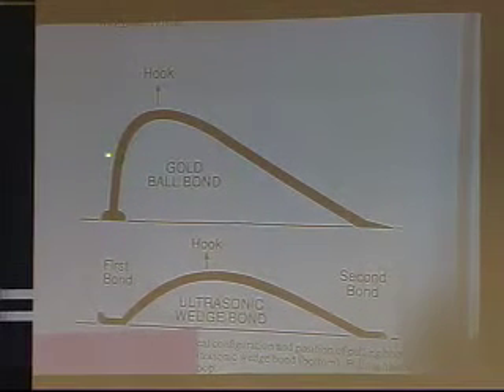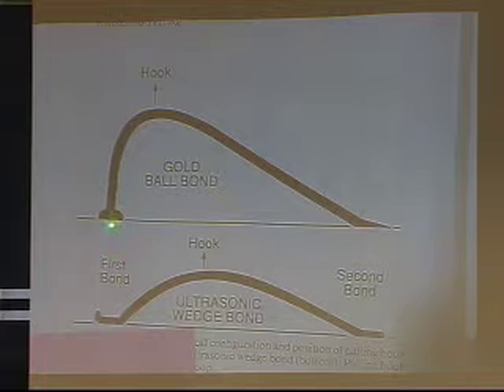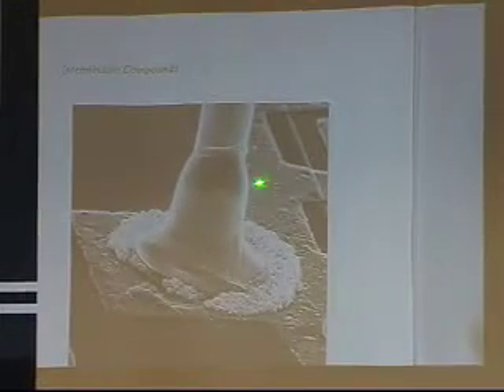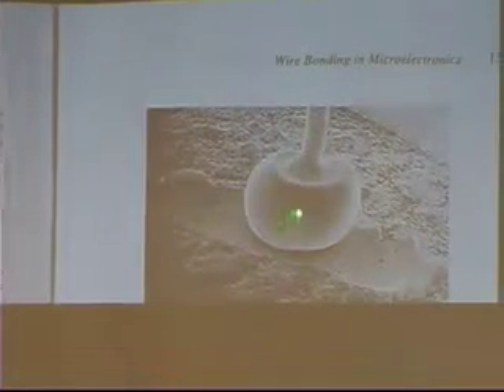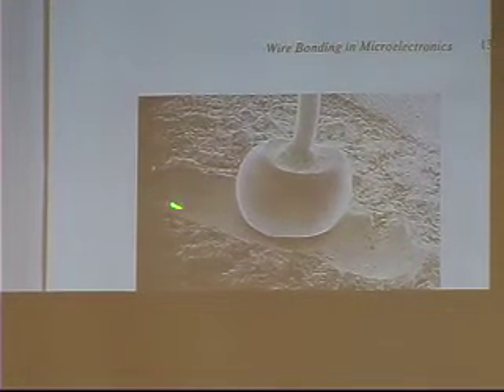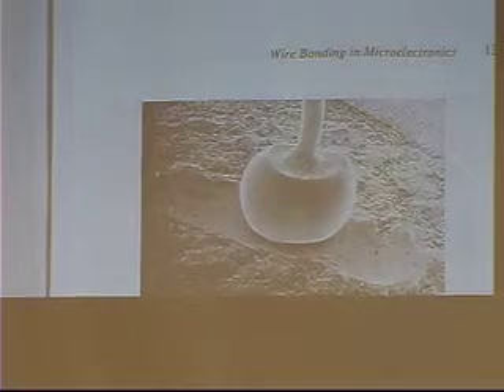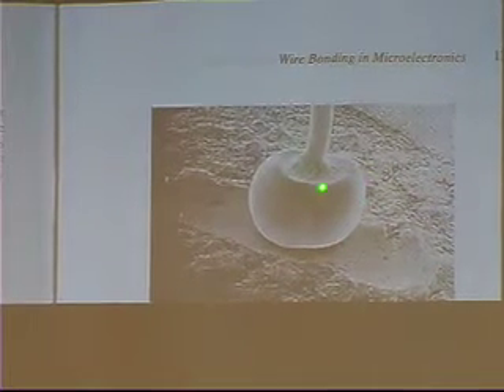Okay, now these bonds are either being made at room temperature with ultrasonic vibration to scour off the surface oxides, or just squeezing that wire against the surface and pushing things aside. And the typical bond might look in the scanning electron microscope like that. This has actually got some corrosion on the bottom of it. Here's one where they didn't mechanically do that. They actually are using some scrubbing action here. They actually scrub the surface to get rid of some of the surface contaminants.